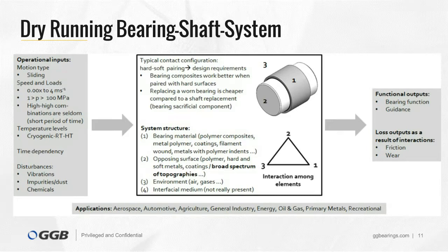The tribo structure is stressed with the operational inputs, which you see on the left side. Another term for the operational input values is the collective stress. The collective stress encompasses the motion type, which is normally sliding for a bearing contact. For each application, we can find a broad spectrum of different loads and speeds. The loads can reach very high levels, we can reach 100 MPa and above. Speed range can also be rather demanding, so we have some applications that go up to 4 meters per second.